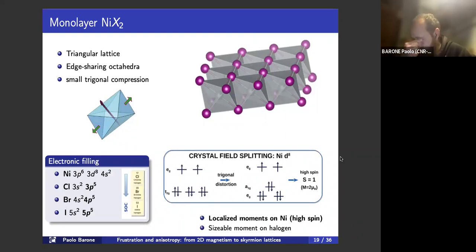In the case of nickel, we can predict the size of the local magnetic moments by considering the electronic filling. So we have to host 8 electrons in the d shell of the nickel in the presence of a trigonally distorted octahedral field. And basically, you see from this scheme that we would have 2 unpaired electrons in the 2-fold degenerate eg levels that would correspond to a high spin configuration with S equal to 1. And this is confirmed by our DFT calculations, where we find that the local magnetic moments are slightly smaller than 2 Bohr magnetons.